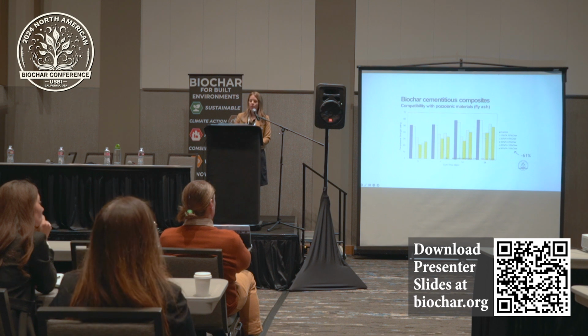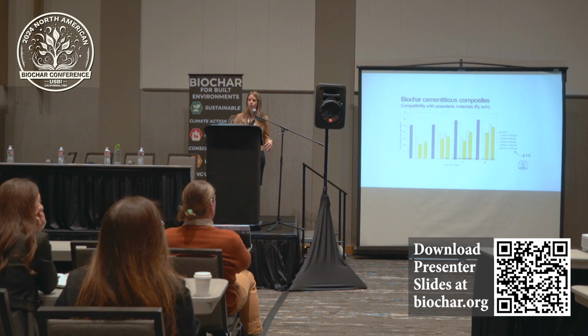And so what we find is when you just replace the cement with fly ash, at 28 days, that's typically your ultimate strength for a traditional concrete, we find that the fly ash is much lower in strength. And this is typical because that pozzolanic reaction takes time. So when you incorporate pozzolanic materials, you typically don't get your ultimate strength until maybe 56 days.